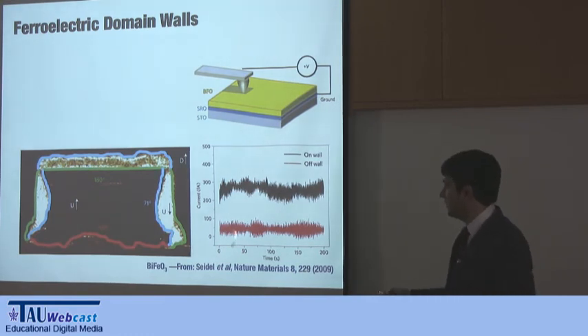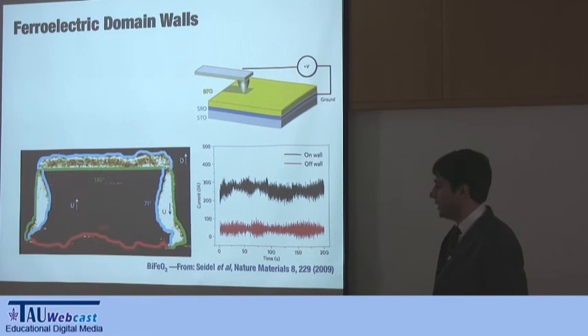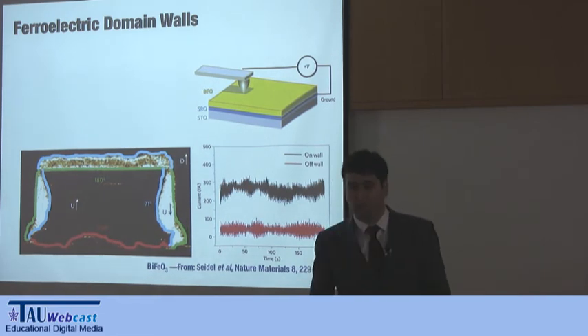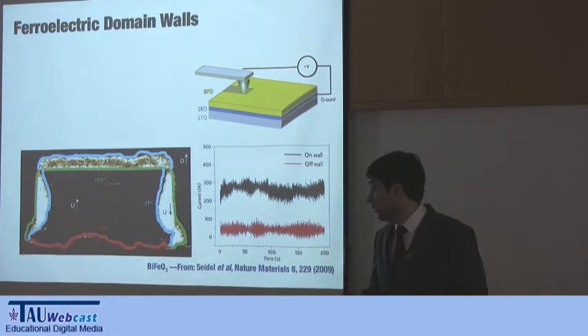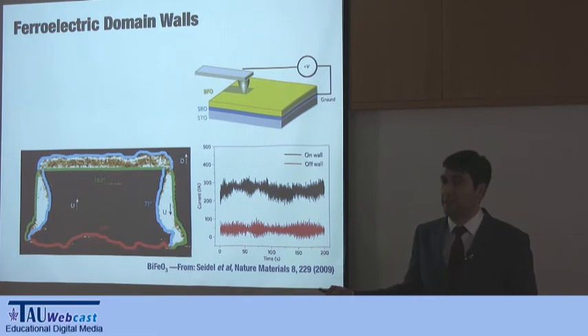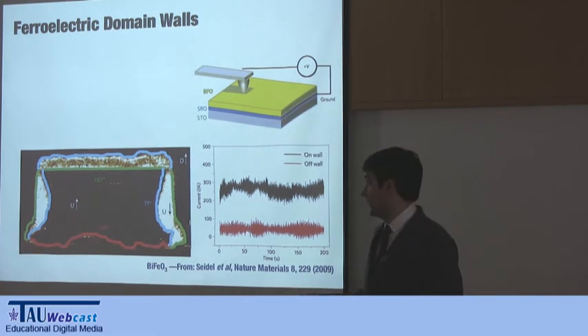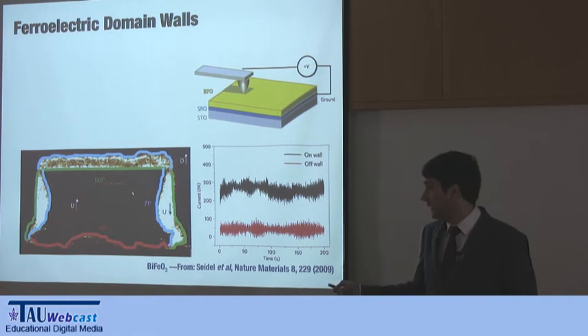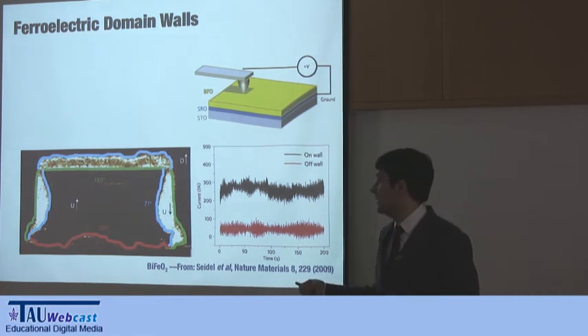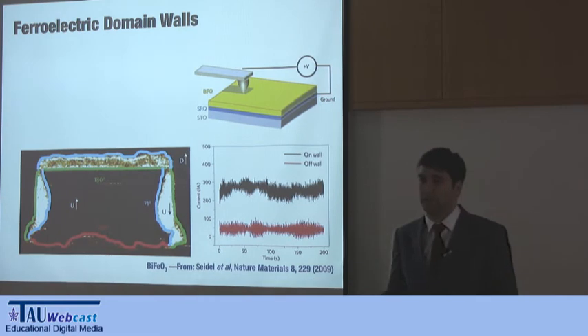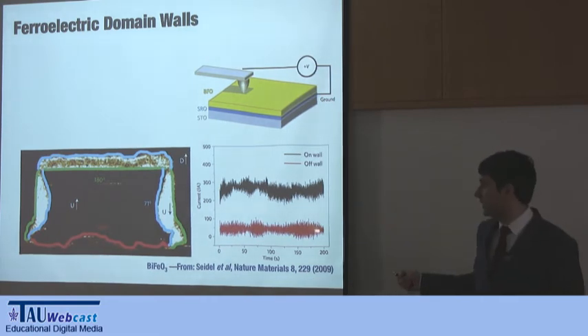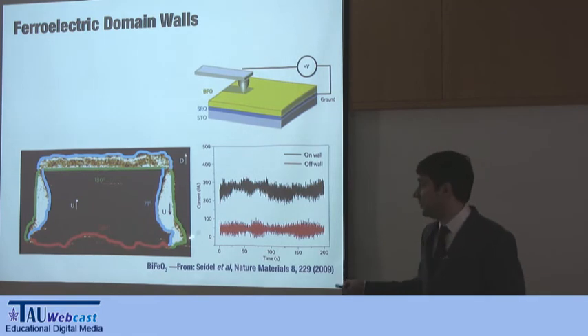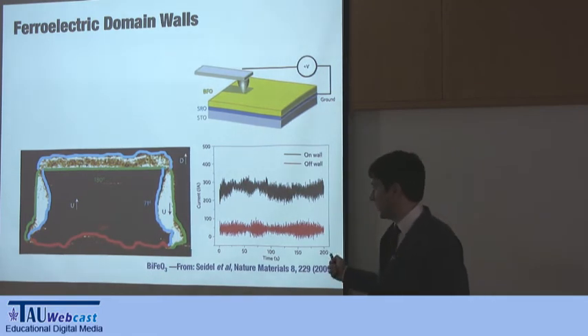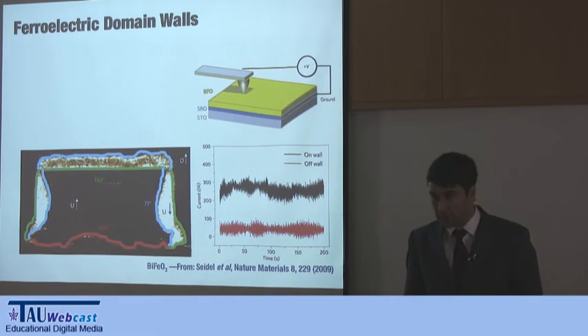And in the case of bismuth ferrite, they have a very unique, at the time, particularity, that is that although bismuth ferrite is an insulator, a clear insulator, with a band gap of 2 to 3 electron volts, the domain walls are conducting. So you measure at the middle of the domain, you find no conductivity. You measure at the domain walls, there is electric conductivity. So why?